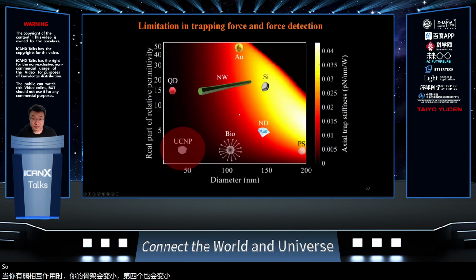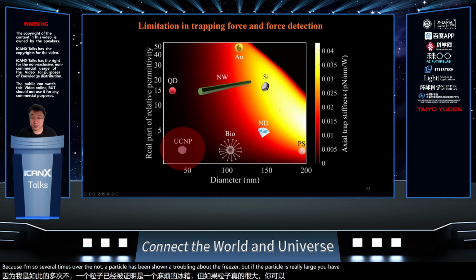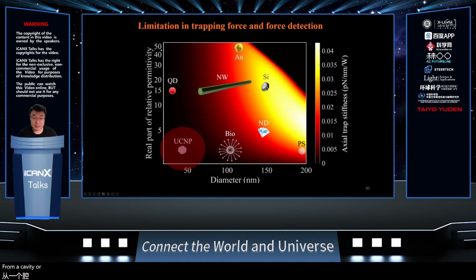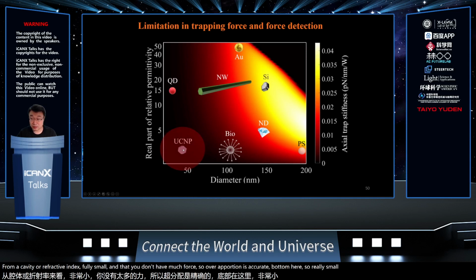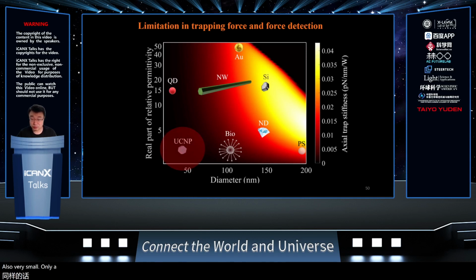So the same applies to trapping some biological particles or even optical conversion nanoparticles, because all of the nanoparticles that have been shown trapped by optical tweezers are large. If the particle is really large, you have a really strong force. When the particle is smaller, you don't have a strong force. And if the permittivity or refractive index is really small, you don't have much force. Our optical conversion particle is actually at the bottom here. It has a really small refractive index, only 1.4, so it also gets limited scattering.